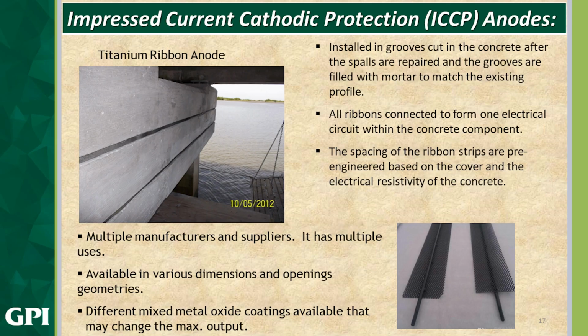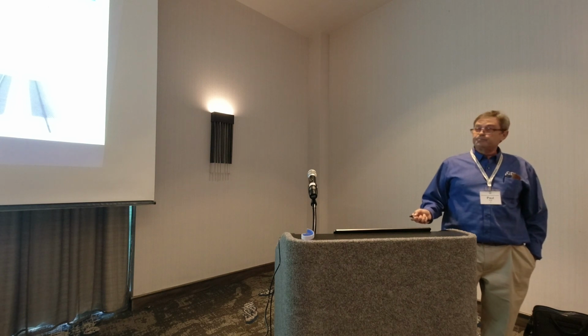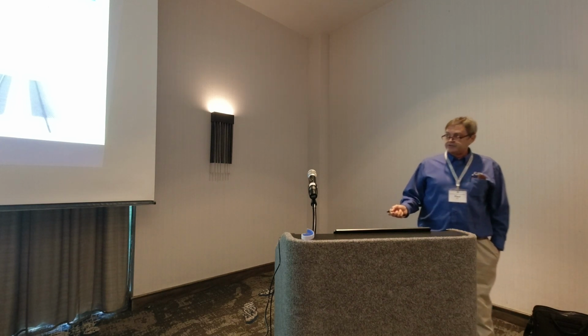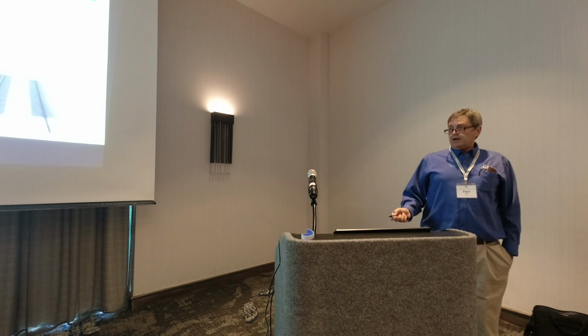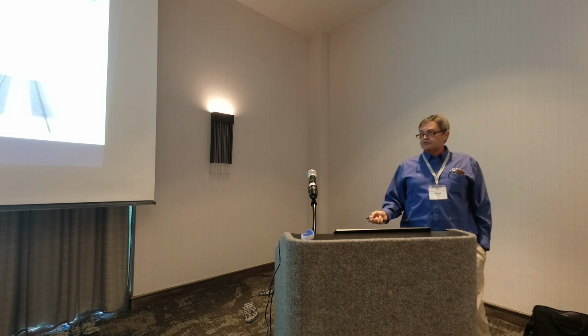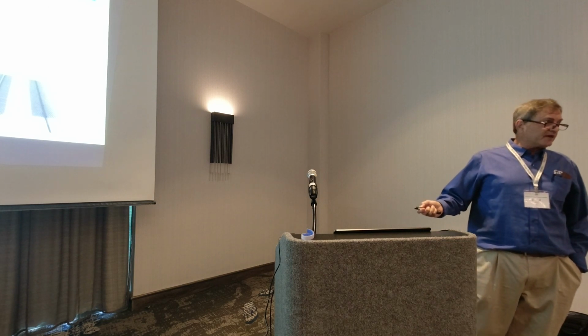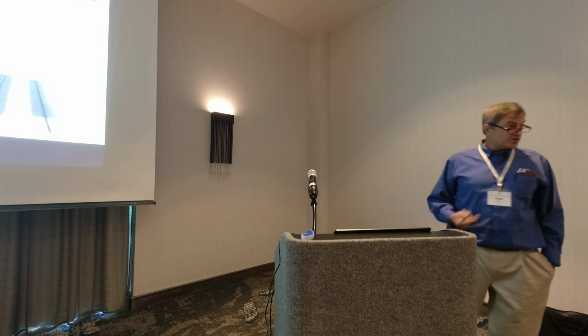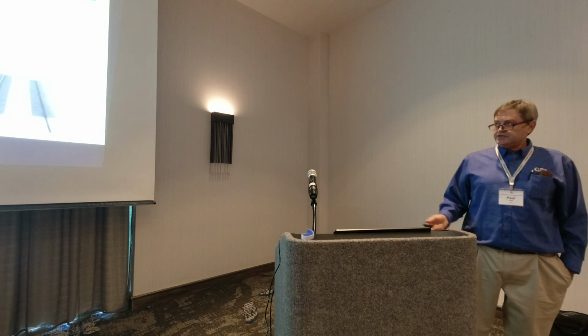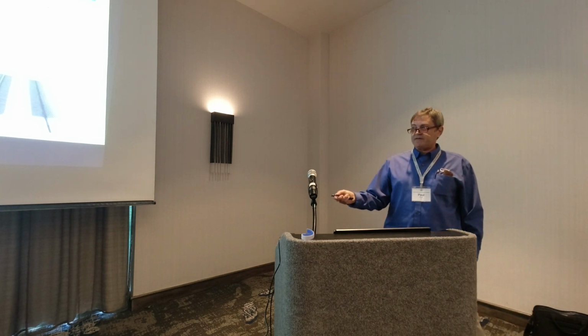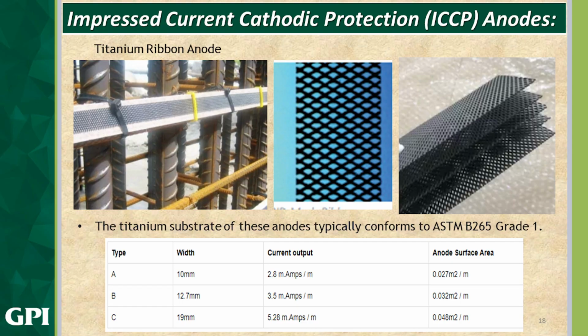Some more on the ICCP anodes. Here's a titanium ribbon anode, where we cut a groove. We place the anode in the groove, and then place the cementitious material over the anodes. Multiple manufacturers and suppliers, and has multiple uses. It's available in various dimensions, openings, and geometries. Different mixed metal oxide coatings are available that can change the maximum output. So how much energy we can send to that anode is dependent somewhat on the manufacturer and which metal oxide was used.